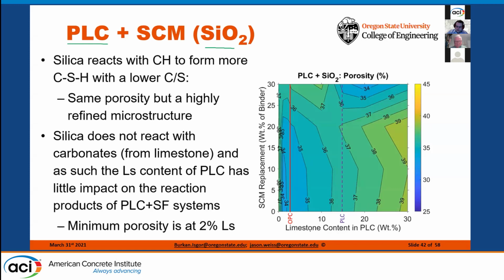I think Keshav did a great job of putting a lot of information on a plot that helps us to really tell a story. On our x-axis, we have the limestone content. So we've got 0 limestone over here at the origin. We get up to about 30% limestone if we go all the way out to the far end of the x-axis. PLCs are shown here as this purple dash, and ordinary Portland cements are in this reddish region. But if we have no limestone in the system, we've got about 38 to 39% porosity.